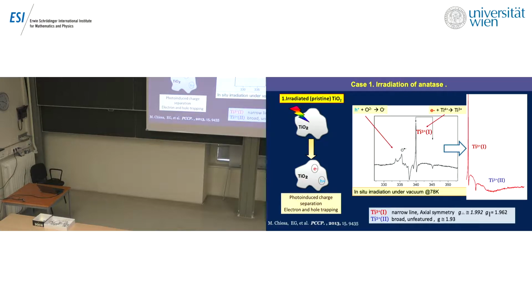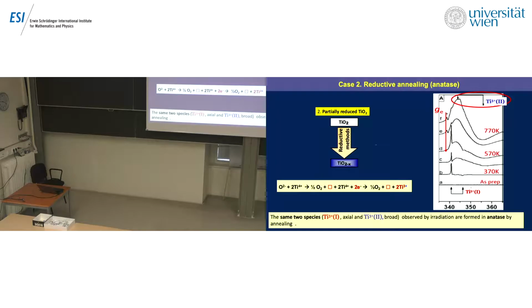And this is an axial system, very nice for doing spectroscopy, but this is a broad one and we have to understand this. The same type of signal appears when you reduce a system by annealing. At the beginning, there is no EPR, the as-prepared sample has no excess electron, and then you start to reduce and the signal 1 appears. But very soon, the broad signal prevails, and at the end of the story it is the second signal, titanium 3+2, in blue in my codex, okay, that prevails.